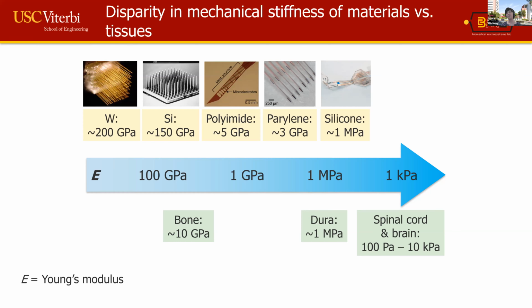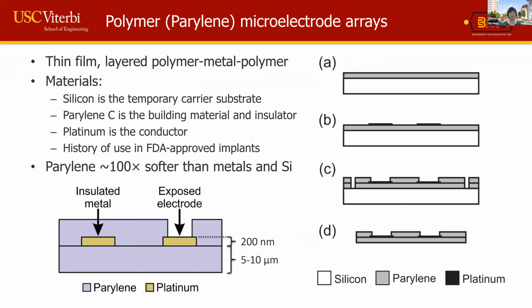If you look on the bottom, these numbers here are Young's modulus. And so as you get to softer and softer tissues like spinal cord and brain, you'll notice that even if you can reduce the stiffness of the backbone that's used to construct the device, you're still many orders of magnitude off. But still, the softer mechanical backbone seems to help. And so the solution isn't perfect, but is a step in the right direction, we hope. And so the approach that we've adopted, and I've shown you a little bit of this earlier, is to take a very simple polymer metal polymer construction and build Michigan-style devices that interface with the brain.